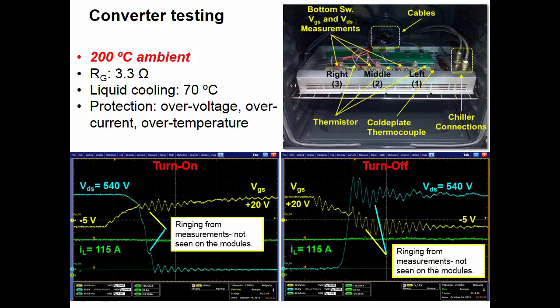In conclusion, a fully high-temperature 50 kilowatt converter was designed, fabricated, and tested. The converter showed good high-temperature performance in a 200 degree C ambient environment, even after soaking for more than 1.5 hours. This work thus demonstrated the feasibility of a high-temperature converter, which could be used in applications such as embedded generators in more electric aircraft.